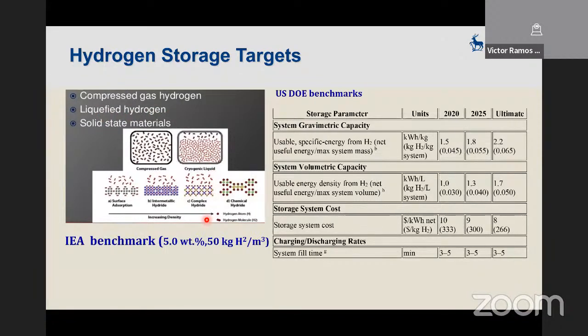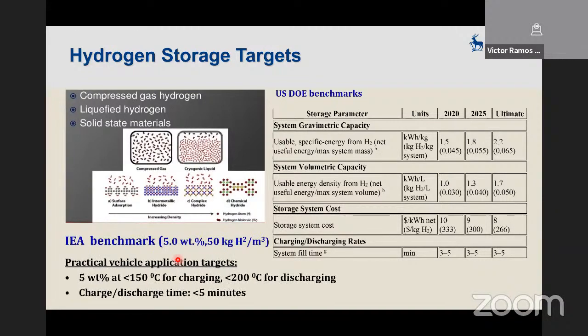So the IEA benchmark is 5 wt%, and 50 kg H2 per cubic meter in terms of volumetric density. But practically, you need to drive the hydrogen off. So the requirement is no higher than 150 degrees. Why 150 degrees? Because the fuel cell waste heat can give you about 100 to 150 degrees. You can very conveniently use it to drive off the hydrogen from the solid materials to feed into the fuel cell.